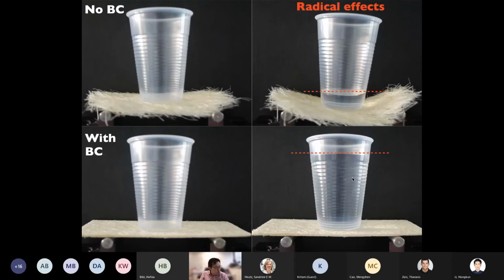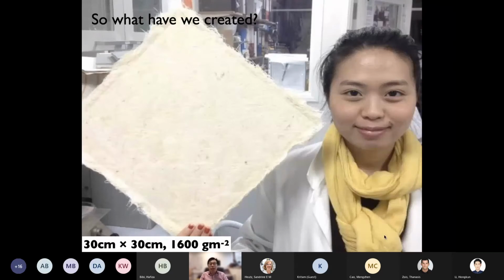We managed to do this experiment with a pint of beer, so with a glass pint of beer as well, and that mat doesn't even bulge or deform at all. And we can actually create a very big preform system, not just limited to small scale experiment. So this thing is a 30 centimeter by 30 centimeter, 1600 grams per square meter bacterial cellulose bound sisal fiber preform, which is bigger than the head of this poor PhD student there.